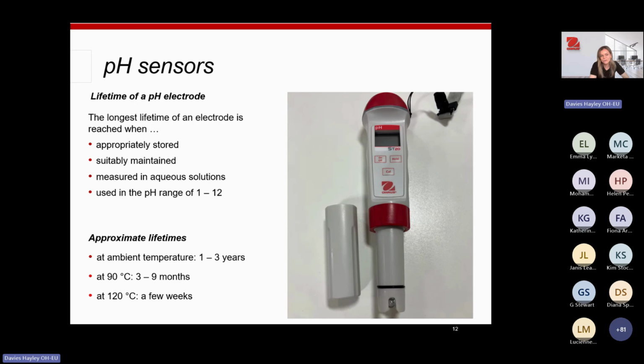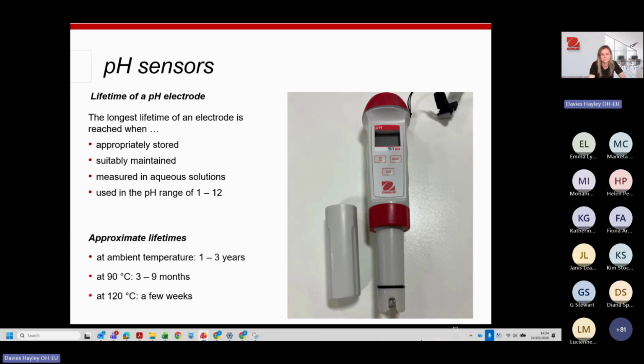And the reason the temperature affects it is because we mentioned the membrane or the tip has a lovely gel layer that's ion rich. If you're submerging your electrode into samples that are high temperature, that gel layer is going to become damaged and frail, and it's going to become dry and crispy and deteriorate quite quickly in high temperatures.